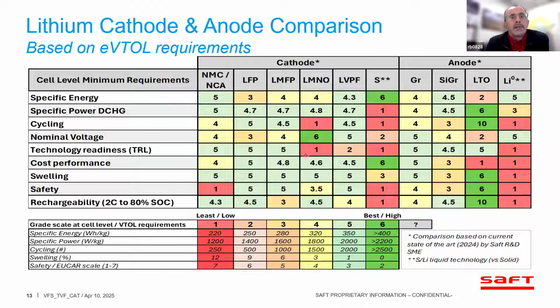You see a lot of really bright green in sulfur, but you also see a lot of red, because the shuttle issue with sulfur has not been resolved yet. So cycling ability is not very good. The lithium metal on the anode side, same: the dendrite formations, very high power, technology readiness. All these criteria are not resolved in a heat map. So what you're left with is chemistry, and this is why you're seeing those NMC and LMFP compounds being considered and used right now for flight.